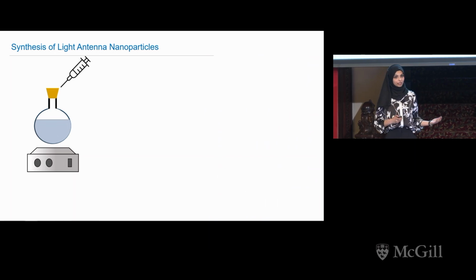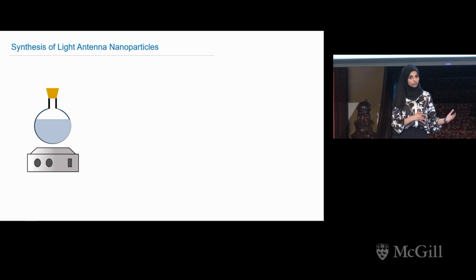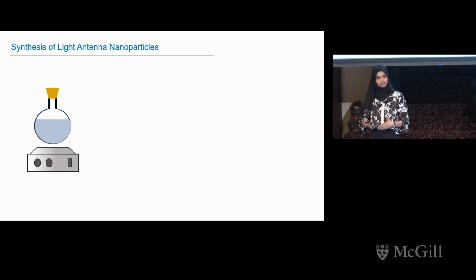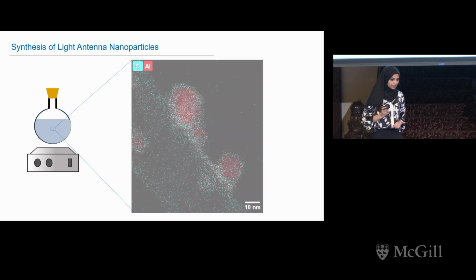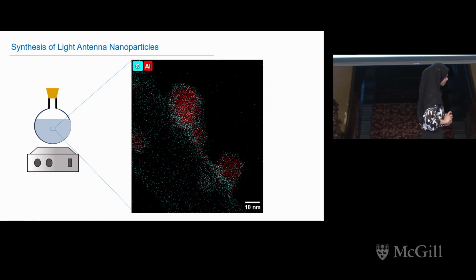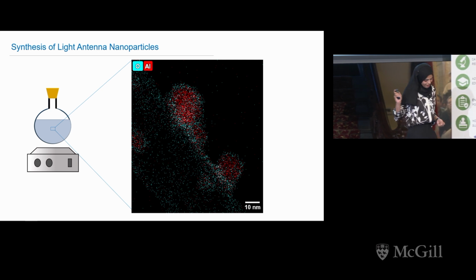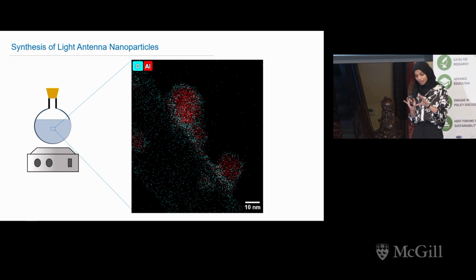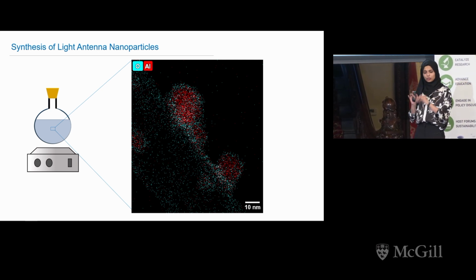Once the reaction was complete, these nanoparticles were washed and analyzed to check if we had synthesized the desired nanoparticles. Here's the analysis result. You see an image showing nanoparticles, small balls with two different colors. The core is red, which is aluminum, and there's a thin sheet of oxygen, which is the oxide shell, and this is what I wanted. This confirms the successful synthesis of my aluminum nanoparticles.